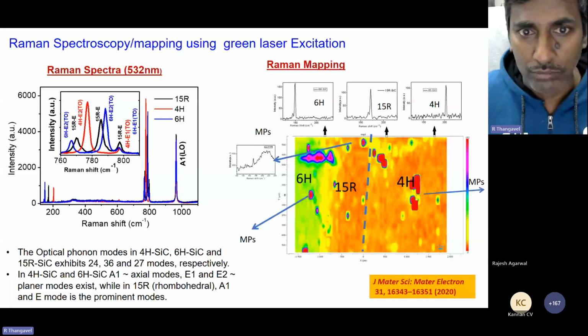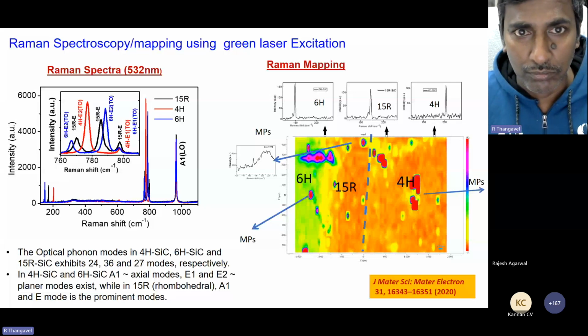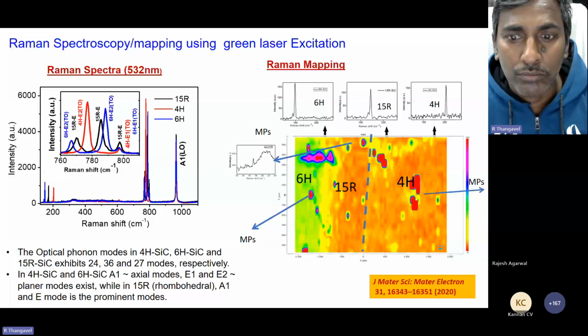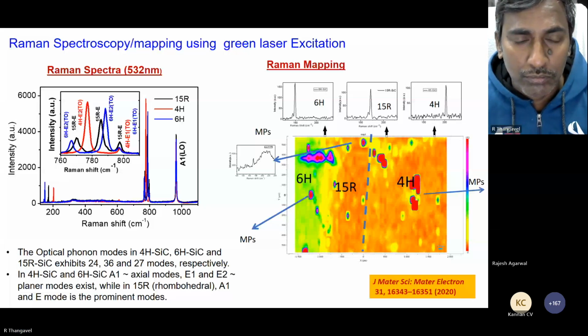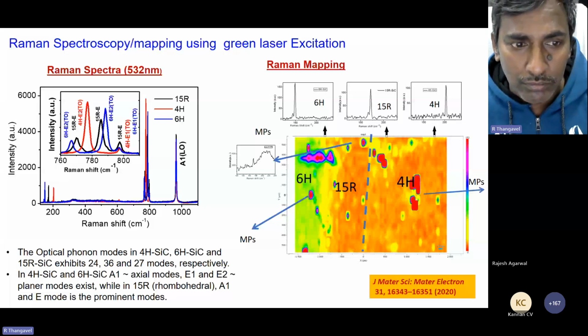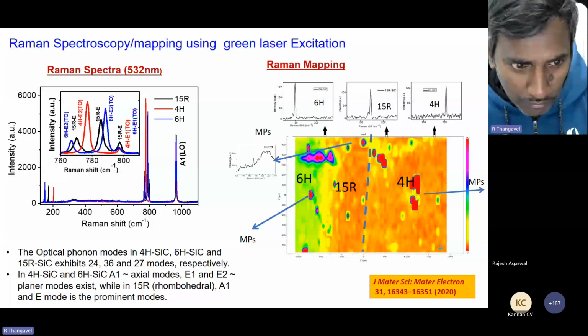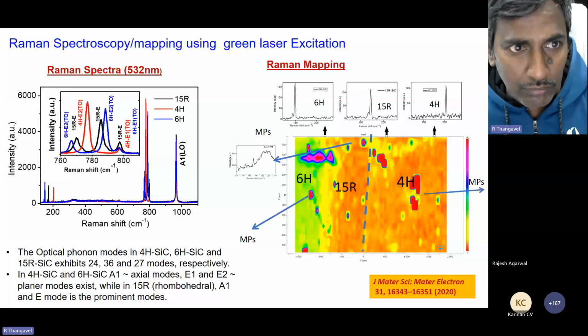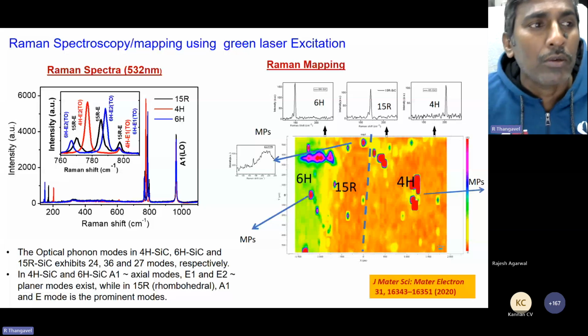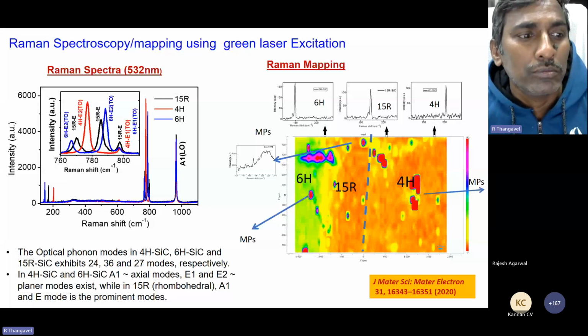Its X-ray diffractogram confirmed that the crystal is cut. So it is a very important characterization technique for orientation cutting of the crystal. And its PL measurement also shows that a defect emission and a band edge emission have been identified.